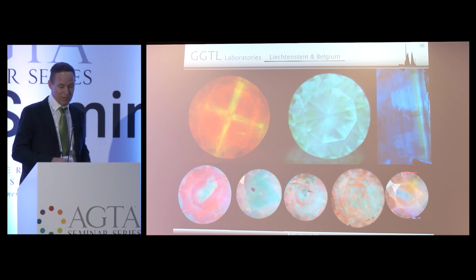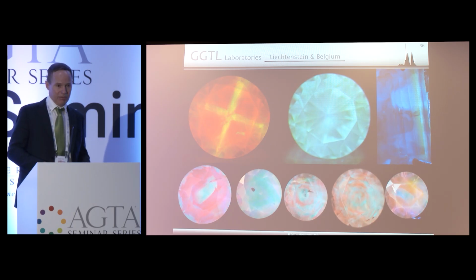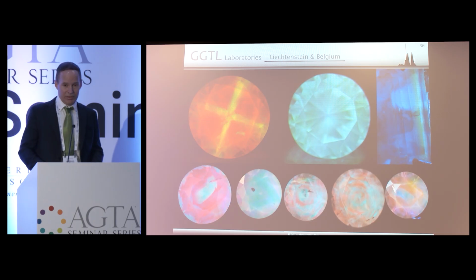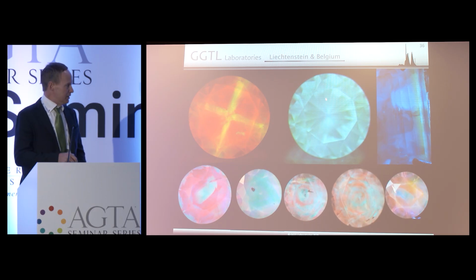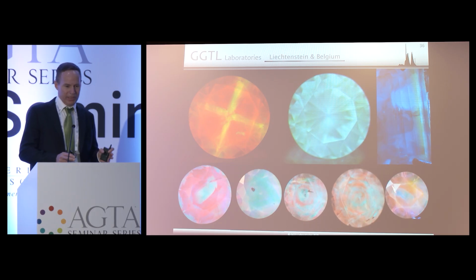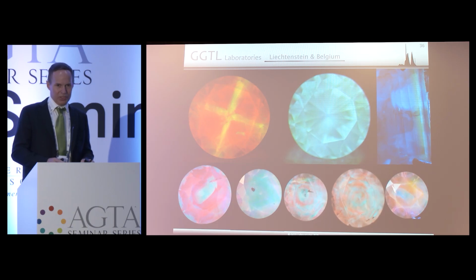Then if you have a green diamond that fluoresces with this strange, chalky, blue-green fluorescence, you take the spectrum of it, and it'll be a really strong band at 523 nanometers. You can be reasonably certain that your stone has been simply irradiated without any heat, because this is an interstitial-related fluorescence that exists only from directly after irradiation until about 100 degrees Celsius. If it gets more heat than 100 degrees, it's gone.